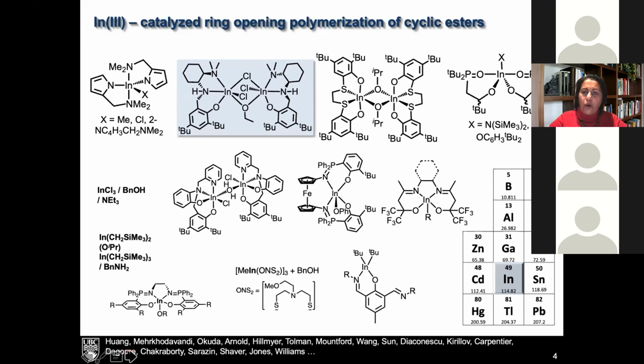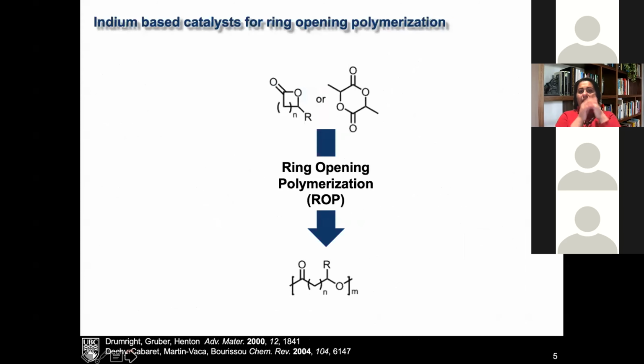So what I think we showed was that we can use indium in catalysis in a really effective way, because indium, being a 5th row, group 13 element, is very resistant to degradation with water and oxygen. I'll show you an example of that. And that had made it a really good Lewis acid to use in a lot of organic transformations. And people have showed later that even when you take that indium and put it in the right ligand framework, you can actually do some beautiful chemistry with indium if you can control certain aspects of aggregation, etc., in the system. So I'm interested in ring opening polymerization in particular, where you take a strained ring.